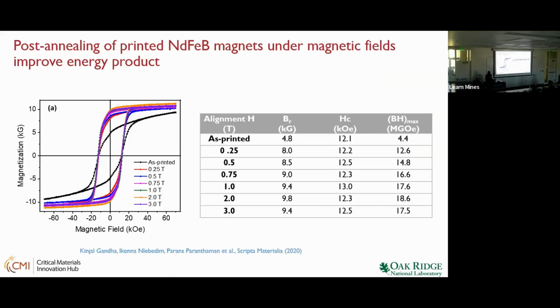The way we work is we work with Ikenna and this team. We print the magnets. The as-printed magnet, if you look at the magnetization, is a little bit weak. The good thing about this thermoplastic is you can go back and reheat. For anything with a nylon or PPS or polycarbonate magnet, you can print a shape or size, anneal it under a magnetic field, heat it and apply a field.